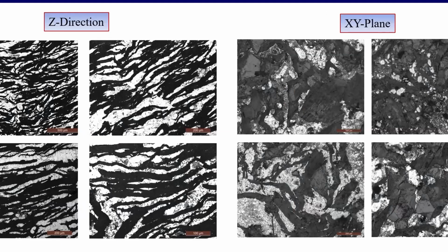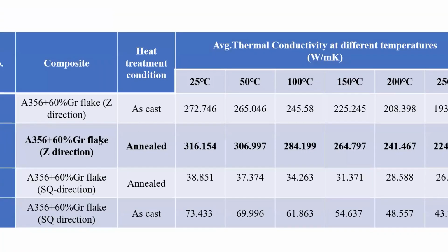Apart from silicon carbide, we can even have graphite. But what are the disadvantages? Graphite is anisotropic. So normally thermal conductivity in this direction will be very high, and in this direction very low, because you can see that the thermal conductivity or electrical conductivity in the graphitic layer is very good. So in the other direction it will not conduct. This is very clear here. If you have the Z direction, that is the graphite aligned direction, you have a thermal conductivity of 316 watts per meter Kelvin. In the other direction you have very low thermal conductivity. So this is an anisotropic property.